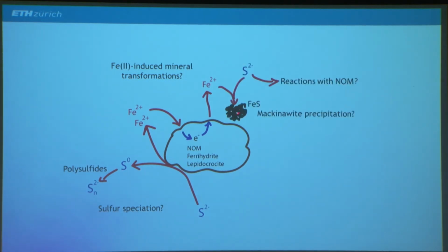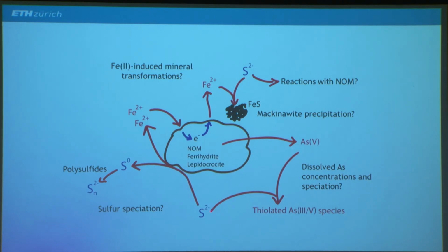Or it could also get precipitated with sulfide if there is enough sulfide to form mackinawite or some polycrystalline iron sulfide precipitate. The sulfide could also react with natural organic matter to form new thiol groups, and those would be very efficient sorbents for arsenic-3. And finally, there could be arsenic release from the flocks, and the arsenic could react with the sulfide to form thiolated arsenic species in solution. And this could be relevant because these thiolated arsenic species are known to adsorb much more weakly than inorganic arsenic species, or than arsenate and arsenite. So it's a quite complex system, and if we want to understand this, we really need to look at arsenic, iron, and sulfur speciation, both in the solution phase and in the solid phase.